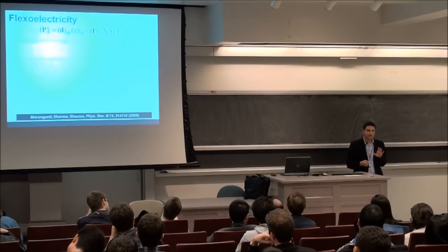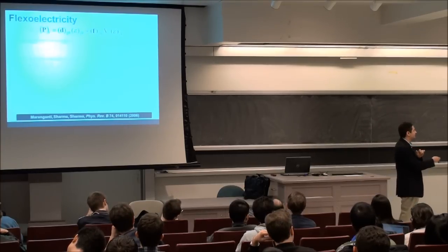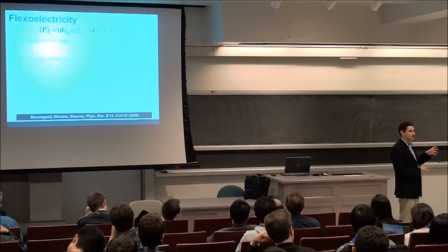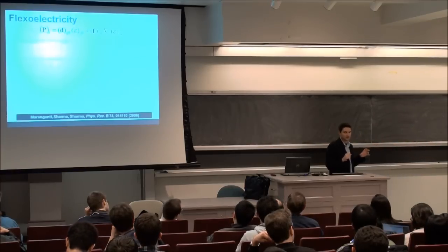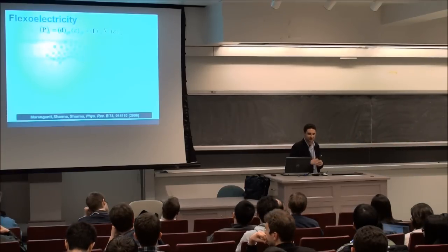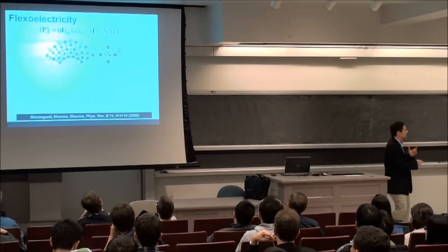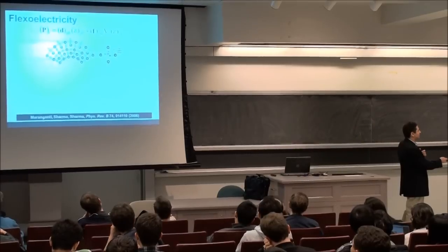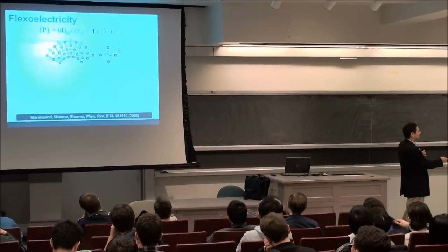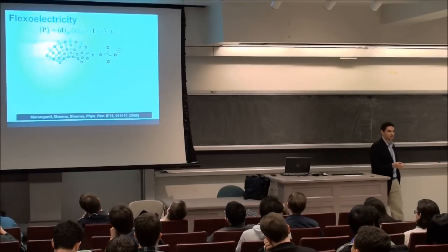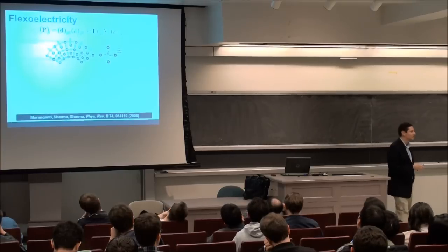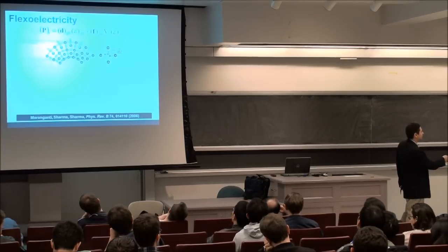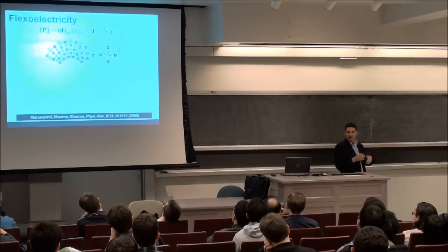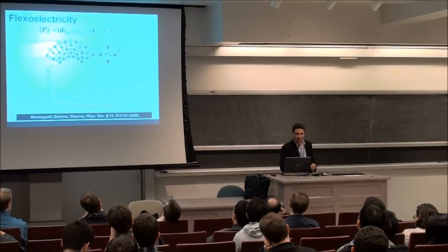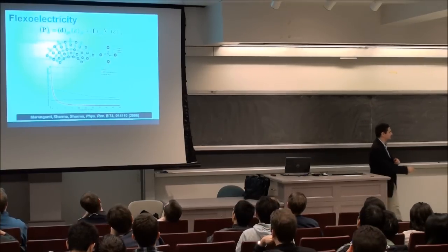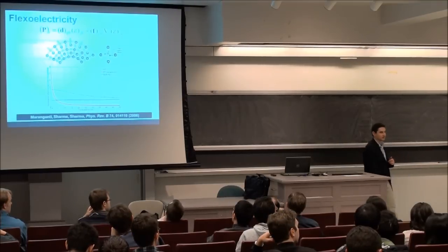In fact, there's even some interest in generating materials which have a zero D value and just look like piezoelectric materials, but they're not actually piezoelectric, just by this flexoelectric effect. Here, for example, is a salt crystal. And as you buckle it, you can see that this buckling changes the symmetry. It gets rid of the centrosymmetric symmetry of the salt crystal. So you can generate polarization by this flexoelectric effect. I just think it's incredibly fascinating. And of course, it scales with nanometer scale. As you go down to nanometer scales, you get a bigger response.